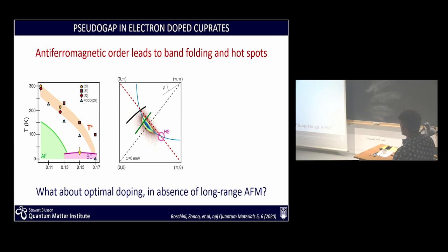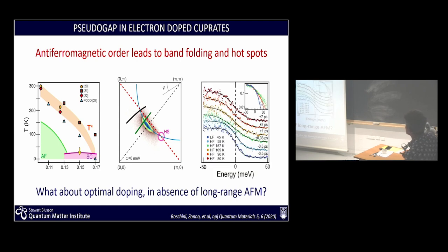So experimentally, we can look at that again, and here you have your Fermi surface at the node, and so we're going to compare data taken along the nodes with data taken at the location of the pseudo-gap itself. In this case, we use the laser similar to what Luca was mentioning before, not just to do a non-thermal effect, but actually to transfer enough energy to the sample to increase its electronic temperature. And so we can look at the data along the nodal direction, and extract a Fermi-Dirac distribution from where the gap is actually zero. Both the superconducting and pseudo-gap are zero here.